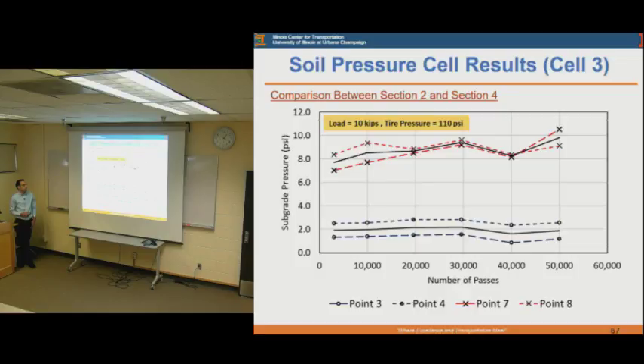For the control section, we're up to 8 psi, and at some points even up to 10 psi pressure on top of the subgrade, which is considered relatively high for the subgrade, and it means that we can be seeing some subgrade rutting in this section.